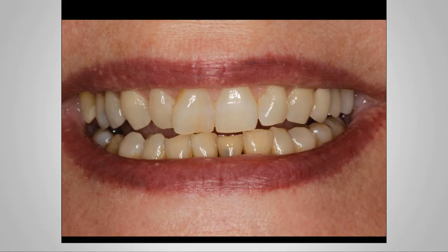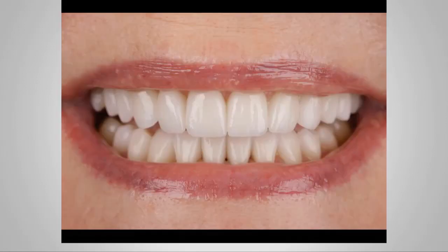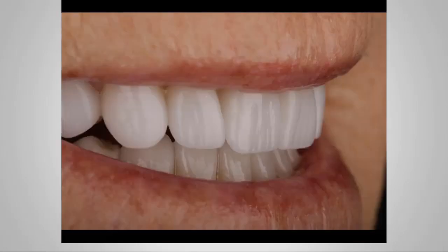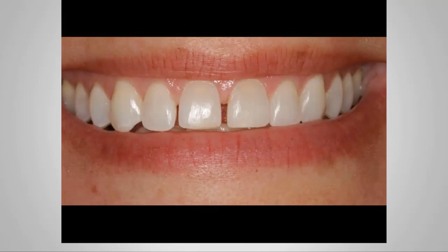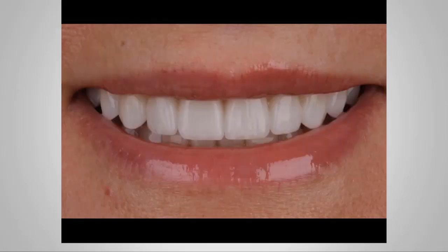This is a typical case that we did with lithium disilicate, and you can see that the aesthetics are great. Nice bonded case. The strength is going to be high, so no question for me, this is still going to be lithium disilicate. Another case, lithium disilicate befores and afters. Once again, veneers, 0.2 of a millimeter thick lithium disilicate veneers. Very nice aesthetic. Without a doubt, my go-to for most aesthetic cases.